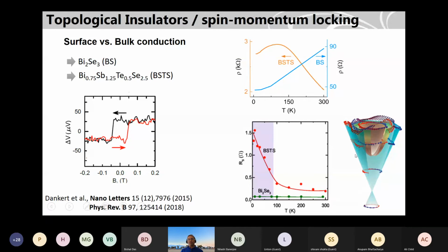So if we look at the literature, we find such a band structure that people have already measured with spin ARPES. And this is the schematic of that. So this is the Dirac band. And if you are here, the spin polarization you get will be very large. But if you are coming close to the conduction band, the Dirac surface states still dominate, still contribute, but also contributions from the Rashba bands in the bulk of the topological insulator can contribute. So this is how you can tune the properties.